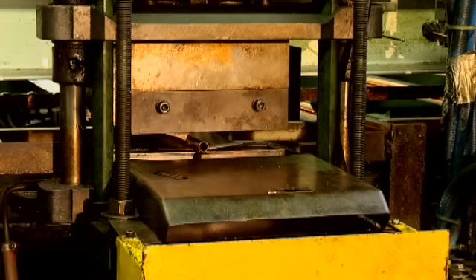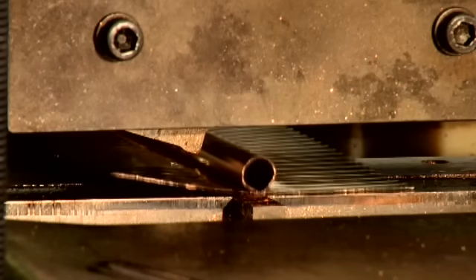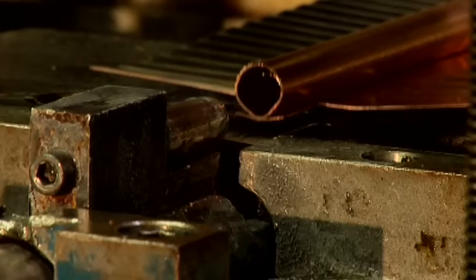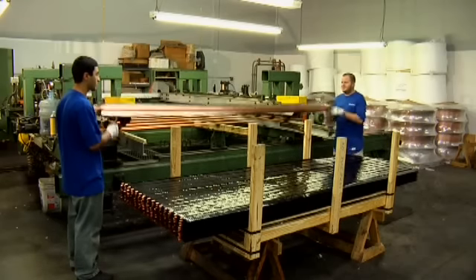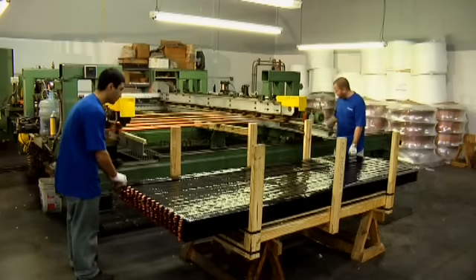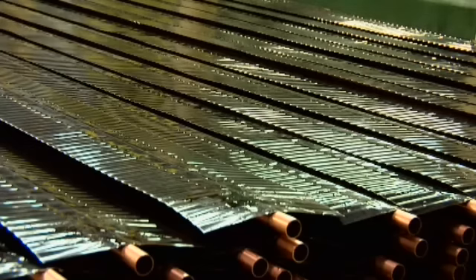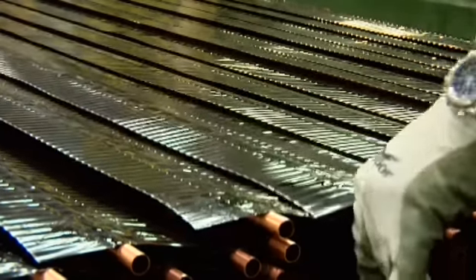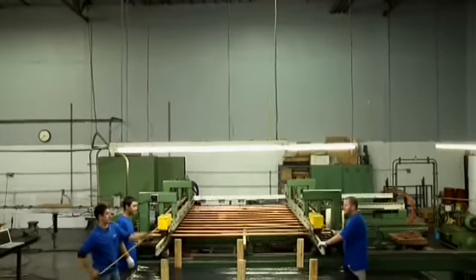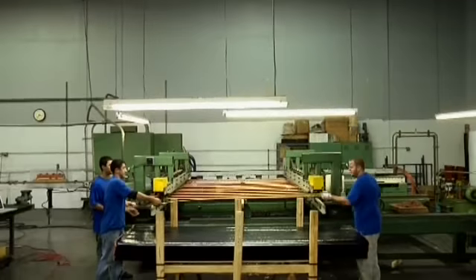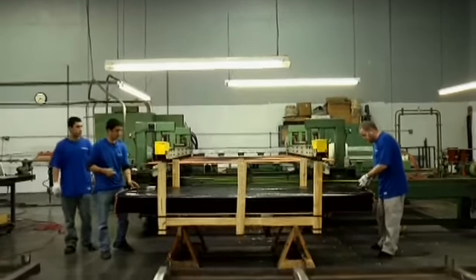In the lateral section, the dual end treatments are performed. They are the crop station, which cuts back the copper from the end of the part, and the skiving station, which removes the material from the end of the tube and re-rounds it. The material is then conveyed to the unload station, where the visual QC takes place and the final product is prepared for crating and shipping. The CTL, when set up, can produce up to 50 feet per minute or 300 absorber plates per shift.